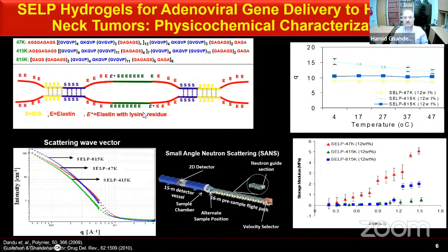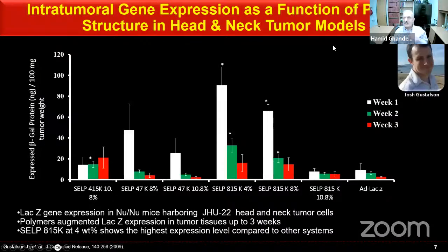The idea is that you can control the modulus, the stiffness of these polymers, by controlling the sequence, but you can also control the degree of swelling. These are after gel formation. You can see that, for example, 815 that has longer elastin units over a period of time actually shows sensitivity to temperature. And we did some basically SANS at NIST a number of years ago to look at the porosity of these polymers. One of the areas that we have used these polymeric materials is for intratumoral gene delivery.